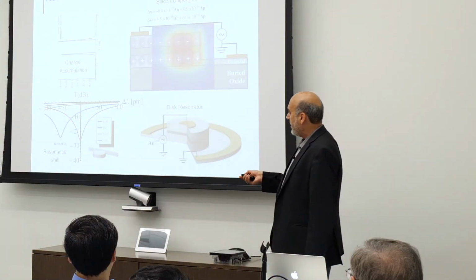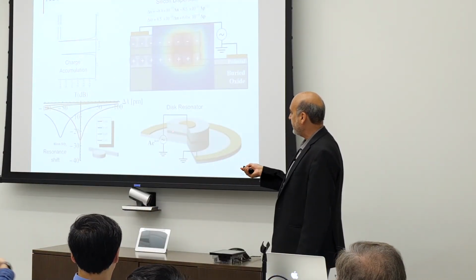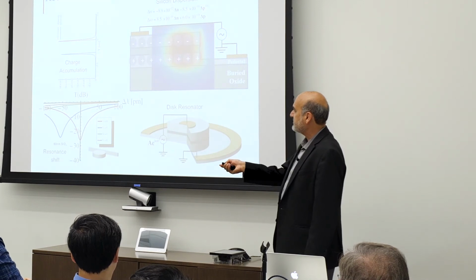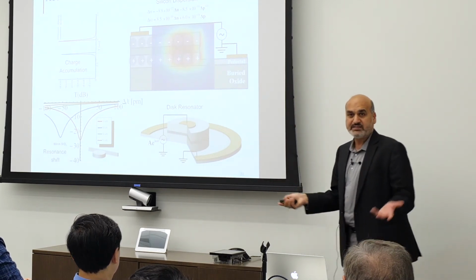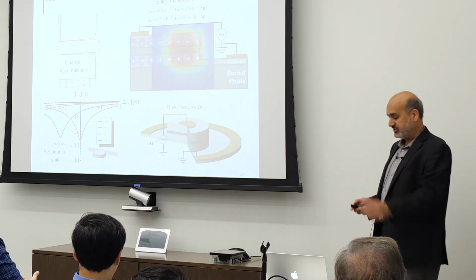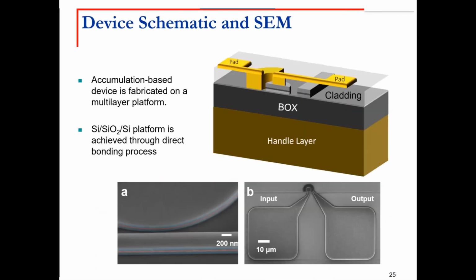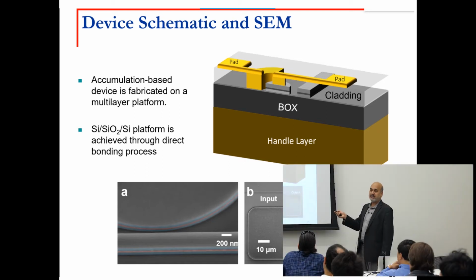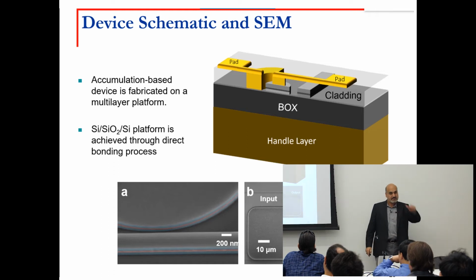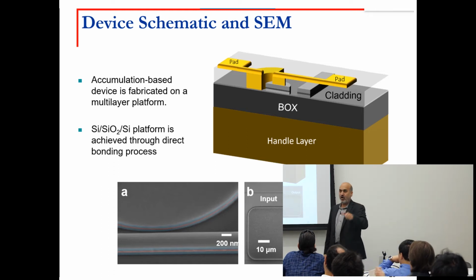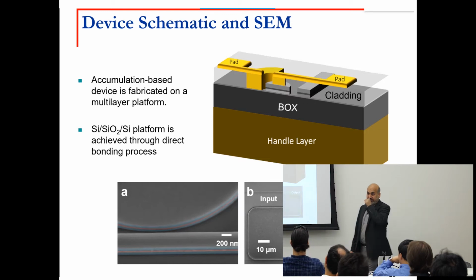This is the example of applying different voltages to a resonator, and then you will see that the resonance wavelength just shifts by applying the voltage as we expect. Index of refraction shifts. So this is the actual structure for fabrication. I didn't get too much into the detail because I assume people are not very interested in the deep technicals. But just to tell you, we always have a challenge of putting contacts in optical structures because metal means loss, and we don't want metal to see our electromagnetic fields.